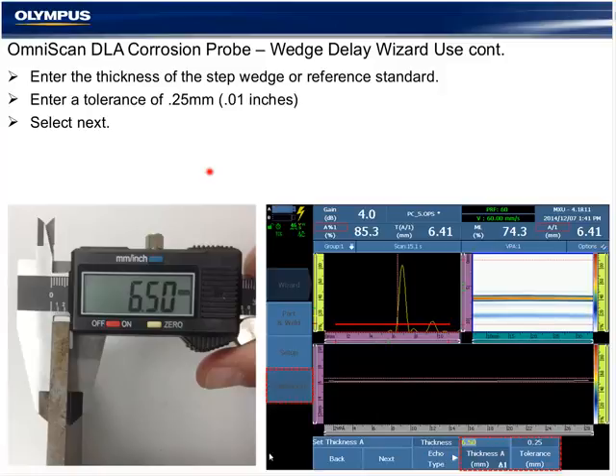If you are using the wedge delay wizard, we want to enter a tolerance of 0.25 millimeters, which is the advertised accuracy of the probe. That 0.25 millimeters is strictly based on us using a leading edge amplitude dependent reading at the gate leading edge position.